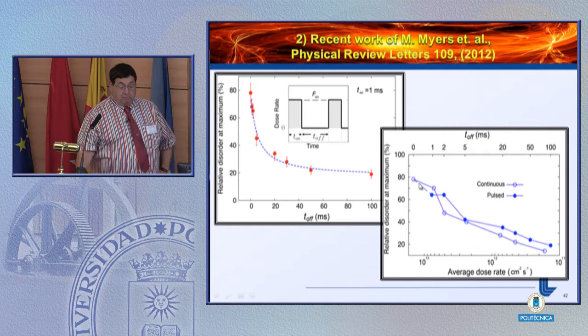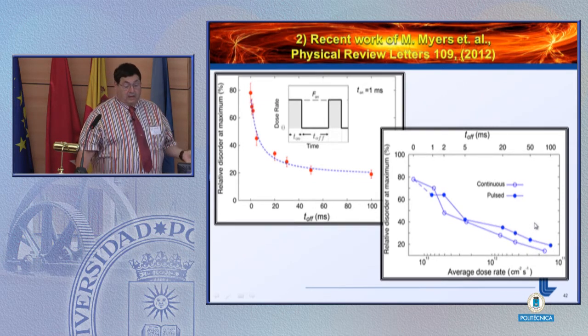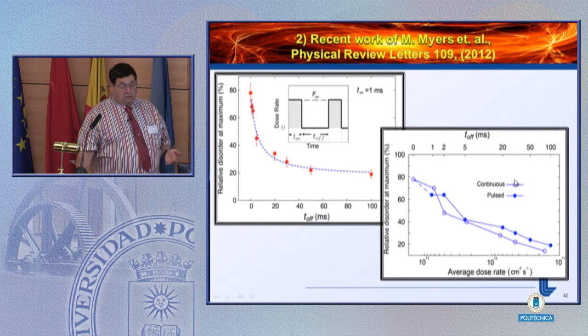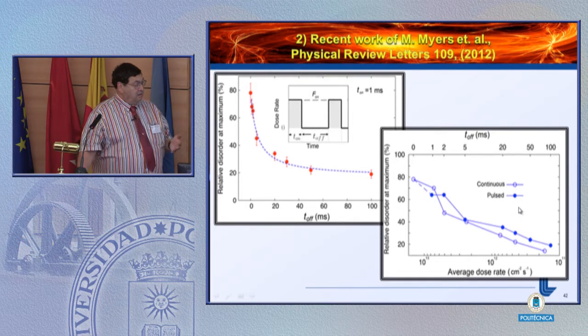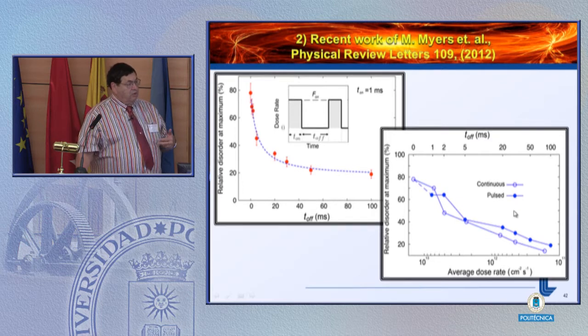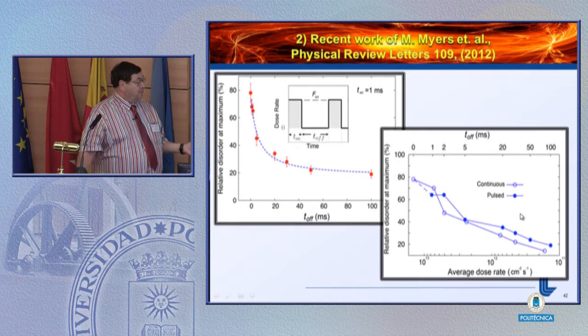And what you see is, by and large, these are as close to collinear as one can expect from this experiment. And that's exactly what you would expect. And in fact, going back in the literature, Trinkaus and others have written papers about this and predicted that in order to see differences due to the pulsing, you would have to go to such high intensities that it becomes almost moot whether that's relevant to anything that you're interested in with regards to radiation damage in nuclear energy systems. It would almost have to be a nuclear explosion.